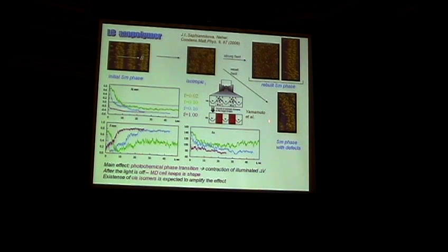And if the field is not strong enough, then we have some smectic-like structure with defects or polydomain smectic structure. So this is quantitatively studied here, where we show the order parameter along the field and the standard nematic order parameter, which we see is dropping down and then again raising up.